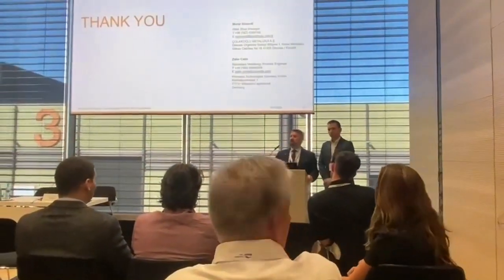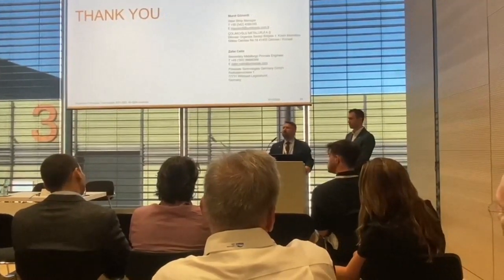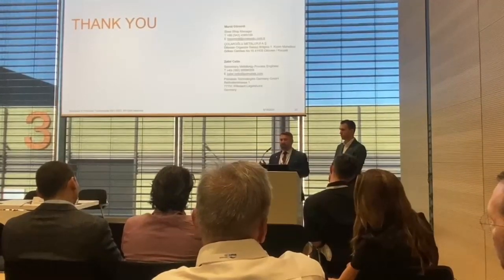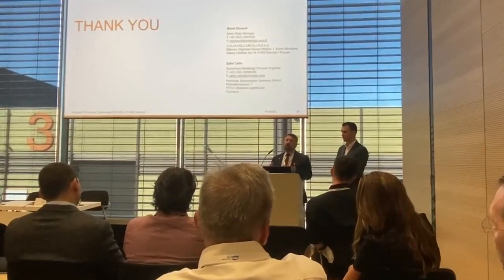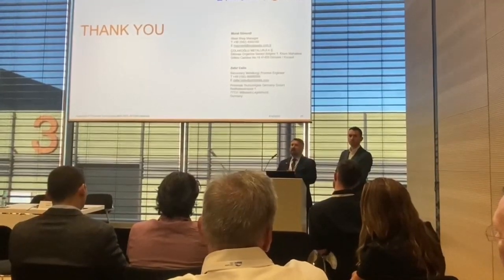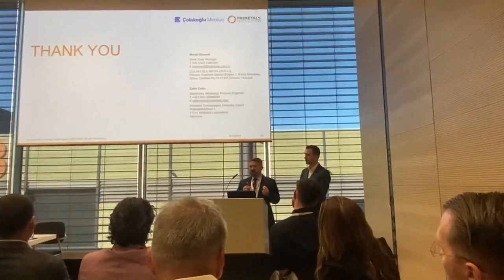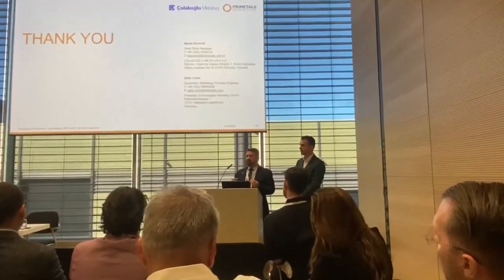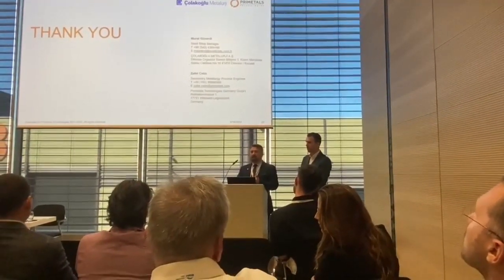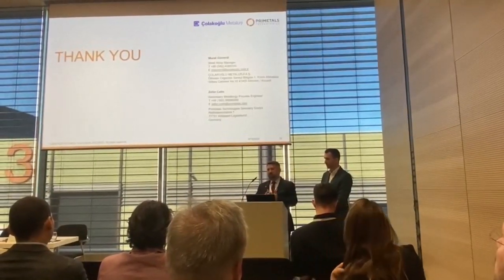Okay, thank you very much. It's a very important point, of course. We use magnesium carbon bricks in the ladle. And we use also the same one for stainless steel, but with low carbon content. As I remember, it was 2% instead of 14%. And in the process, the carbon pickup is related with the steel temperature. So after the VOD process, when we measured the temperature, we immediately calculated the required cooling scrap, and we put it into the ladle as fast as possible.